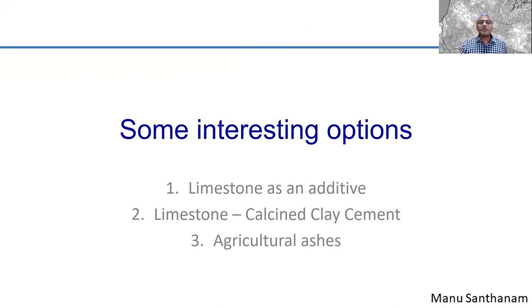I'll talk primarily about limestone as an additive, and you know very well that limestone is the primary raw material for the manufacture of cement. So it is a global solution as a supplementary cementing material, because limestone is going to be available anywhere that cement is manufactured, right? Now, calcined clays can present a very nice alternative to something like fly ash, which is very slow to react, whereas calcined clays tend to react much faster. But recent research at IIT Madras and elsewhere in the world has shown very clearly that combinations of limestone and calcined clay as a large volume replacement of the cement can still produce excellent properties of the concrete.